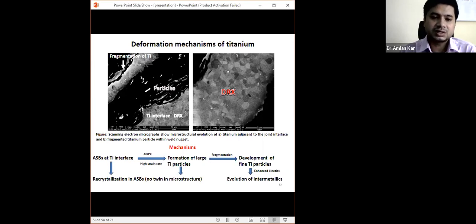It's close to 1000 degrees centigrade, and this temperature evolution takes place only in titanium. It's not a global temperature, it's a local temperature in the titanium. So because of the evolution of high temperature in the titanium, it is subjected to recrystallization. It is called dynamic recrystallization. At the same time, since the adiabatic shear band is an inhomogeneous deformation process, that leads to the development of cracks in the titanium, and while deforming, the propagation of these cracks leads to the formation of fine particles, and that's why we get different kinds of particles.